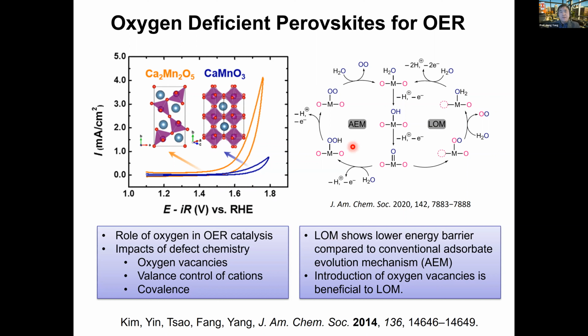Now you will see, if you analyze, at least two competing mechanisms for the oxygen evolution reaction. One of them, of course, is the so-called adsorbate evolution mechanism. This is the one I proposed, which was proposed earlier, focusing on the electronic structure primarily. But for the lattice oxygen mechanism, the main difference, if you compare it to that, is that this empty oxygen site can be replaced and be mobile. So this oxygen can participate in the reaction.